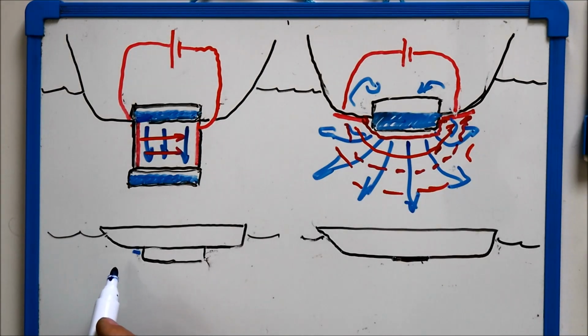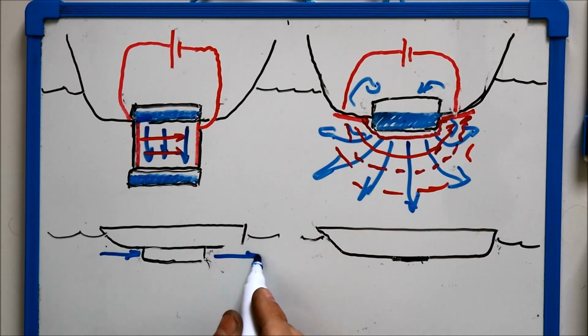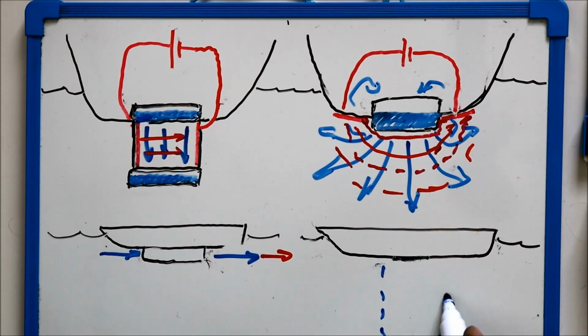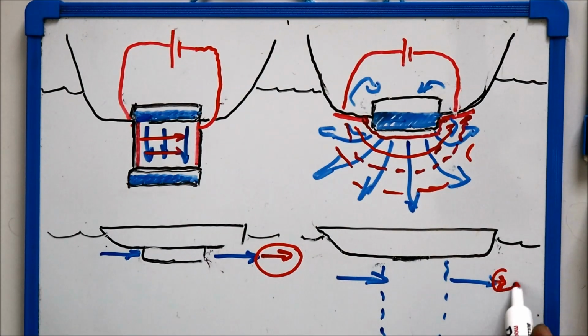Now, to generate a specific amount of propulsive force, a certain mass of water has to be sucked in. That flow gets accelerated as it leaves the back of the duct, and Newton's second law gives us thrust. In this external flow configuration, the electromagnetic force acts on a much larger piece of water, a larger mass. So to generate the same amount of thrust, it only needs to impart a very small amount of acceleration to that mass. This increase in velocity in the wake represents energy that you can never recover. So the less energy you impart to the wake, the better the efficiency will be. So this external flow configuration definitely has an advantage as far as efficiency is concerned.